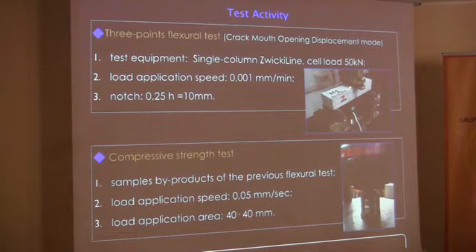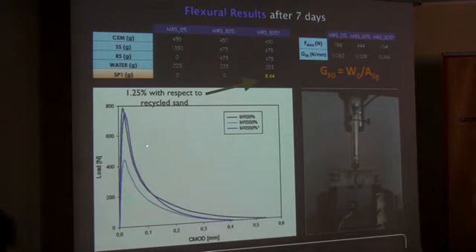We performed notched three-point bending tests, and then on the two halves a compression test was performed. This is the first series in which we try to observe that when we add 50% of the recycled sand, of course the strength decreases a lot. This is because we maintain the same quantity of water, but the sand requires a lot of water. So in order to obtain a good workability, we need to increase the water. If we increase the water, of course, we decrease the strength.